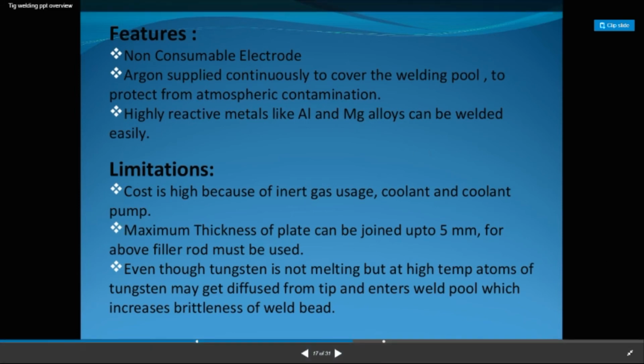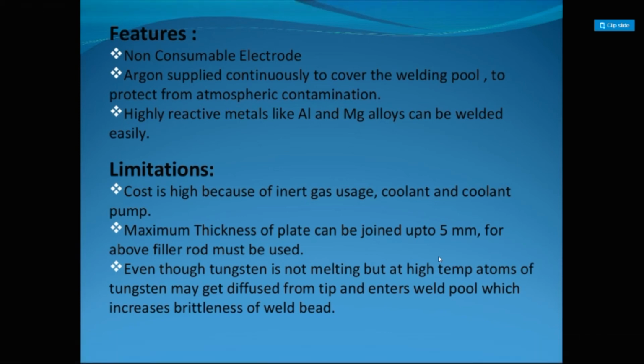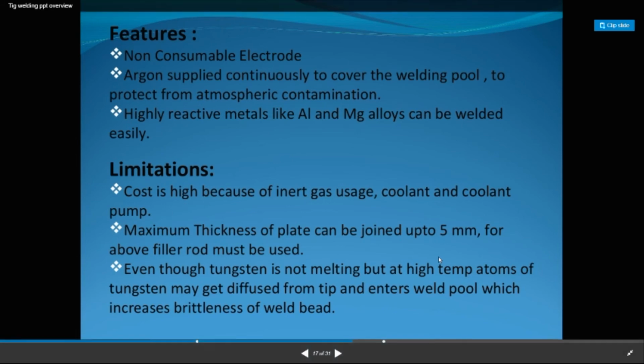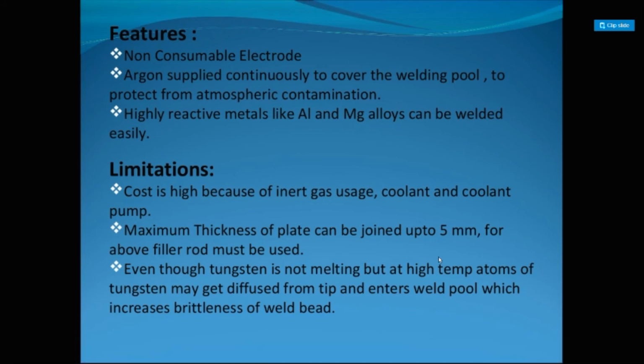What are the limitations? Cost is high because of the inert gas use, coolant, and coolant pump. The maximum thickness of plate that can be joined is up to 5 mm; above that, filler rod must be used. Even though tungsten is not melting, high temperature atoms of tungsten may diffuse from the tip and enter the weld pool, which increases the brittleness of the weld bead.